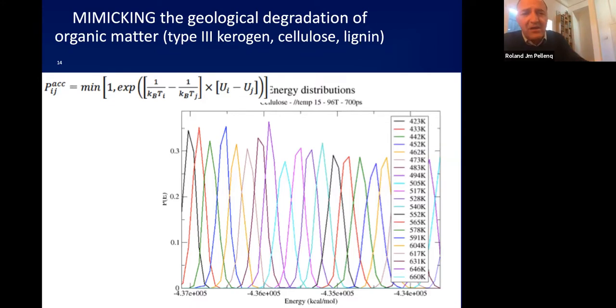This is very simple. We calculate the difference of the reciprocal temperatures, times the delta of potential energy, and we compare this quantity with a random number taken between 0 and 1. The Monte Carlo procedure is very simple. If that exponential, called the Boltzmann factor, is larger than the random number, then we accept the move. If not, we reject the move. And then we proceed this way. So basically, we are exchanging the configuration from high temperature to lower and lower temperatures. In the end, the observation temperature is the one we choose, which is typically the lowest of the temperatures that we are considering for all the processors.